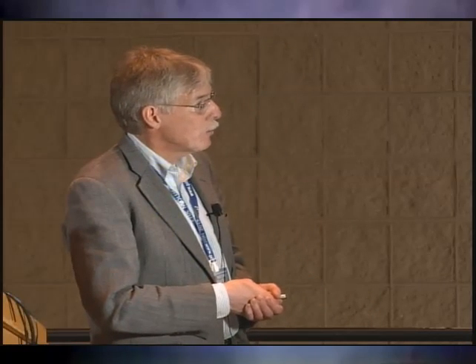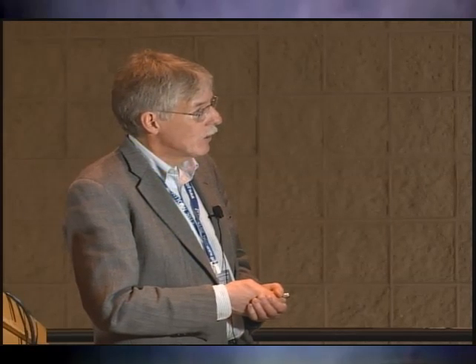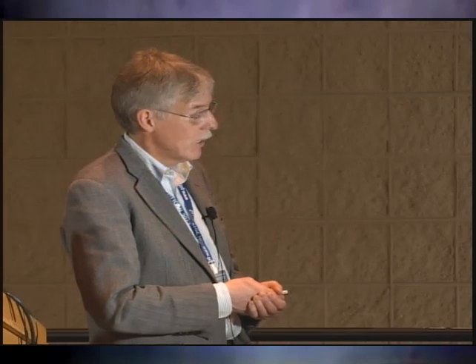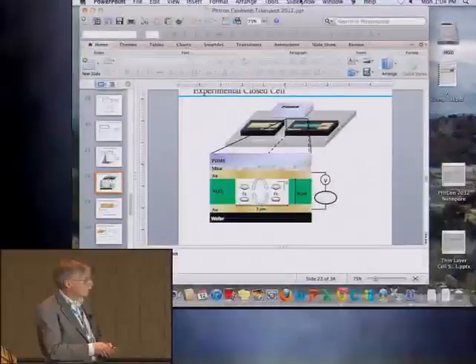If you have an open cell, you can use microfluidics to pump stuff in, but in that case, ions have access to the solution. They can move in and out, and it's not the same problem that we're trying to study. So what we do is we build the bottom part of the cell, and then we take a piece of PDMS, fairly thick, and we glue a sheet of mica to that, and the mica is about a micron thick. It's basically Saran wrap, or thinner than Saran wrap, and deposit gold on top of that.